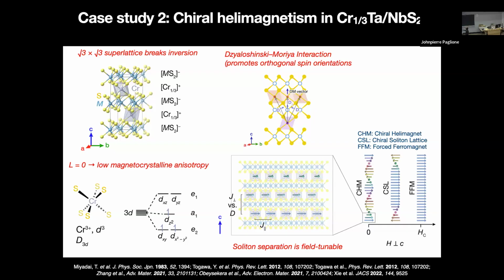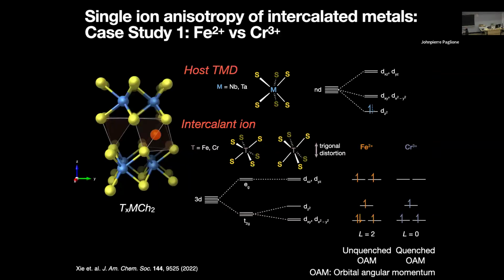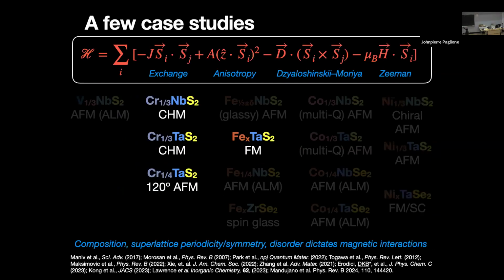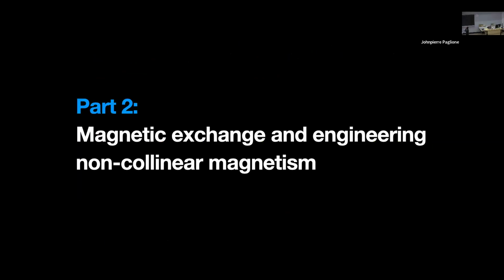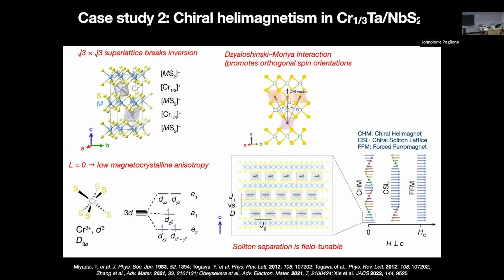And so that then allows you to have a non-zero Dzyaloshinskii-Moriya term, right? That term relies on broken inversion symmetry. And because it's the cross product here, it promotes or drives the system towards an orthogonal orientation of spins. And the combination of that with the magnetic exchange is going to lead to canting of the moments in the material. So here is the Dzyaloshinskii-Moriya interaction, which promotes orthogonal spin orientations.